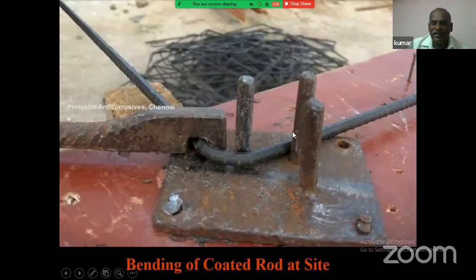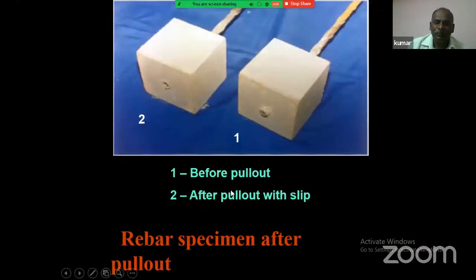See, this is again in the site, how the people are doing it. Even then, this is not all a problem. This is a pull-out strength test. Before pull-out and after pull-out, the slip is measured and correspondingly compared with the uncoated system.